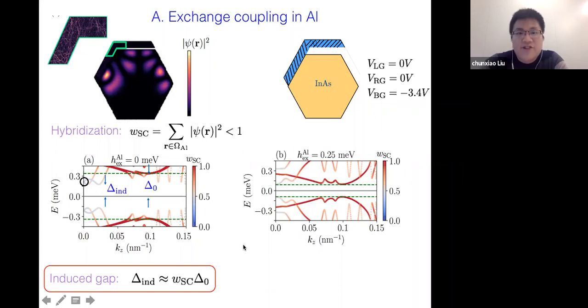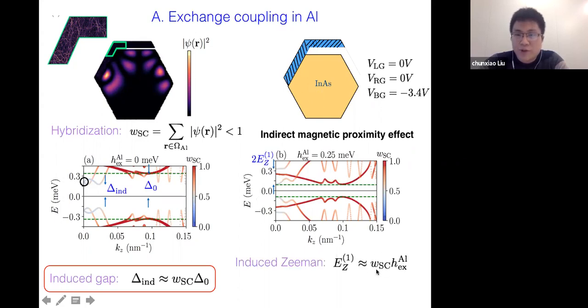So there are a few observations here. First, the spin orbit degeneracy point here is lifted by an induced Zeeman energy. This effect we call the indirect magnetic proximity effect, because this means the hybrid state is induced with a finite Zeeman energy by distributing its wave function inside the magnetized aluminum layer, although it has no direct contact with the europium sulfide in this particular scenario. So this is the way of inducing Zeeman energy for the hybrid state, and its strength is also proportional to the weight in the superconductor.